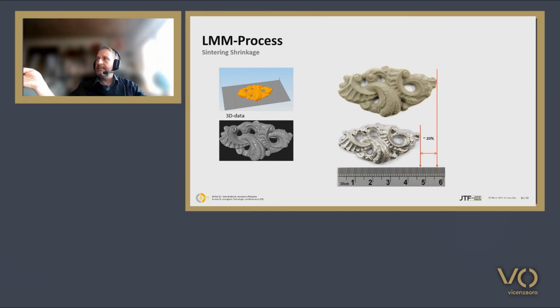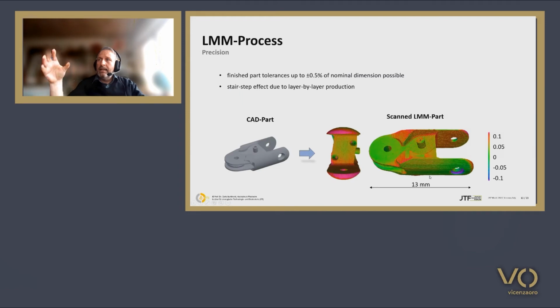And because it's a 3-dimensional shrinkage that's the same in all 3 directions, it's very simple. So you blow up your CAD data by the shrinking factor, so that in the end you get your final part. So you compensate for that shrinkage. As I said, the parts are very precise.